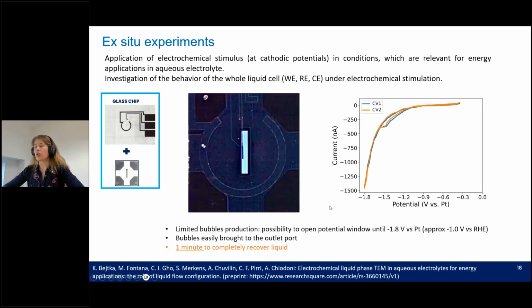Let me show now the same or similar experiment, but done with the modified flow configuration. So the glass chip is interfaced with the small modified chip. And here we can see that we can open the potential window more. And this is thanks to the fact that we have more electrolyte where the reference and counter electrode are placed.